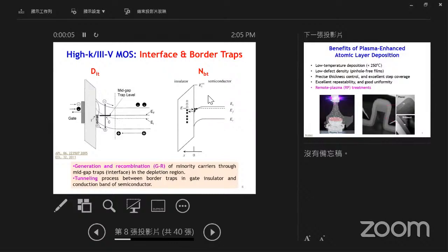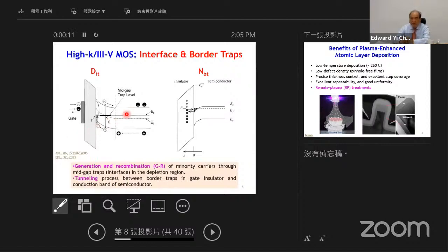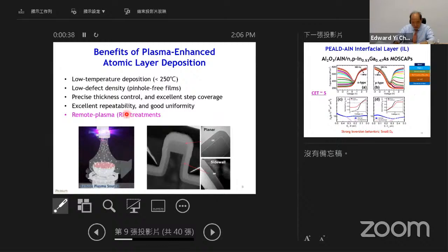Okay, so we're talking about the high-K and the III-V. The interface has many problems, including the interface trap density and also the border traps. These will cause some generation and recombination through the midgap traps, and that will affect your VTH. Also the border traps may tunnel into the semiconductor, and that also will affect your VTH. So the solution to this is you need to have a high-K material with very low interface traps.